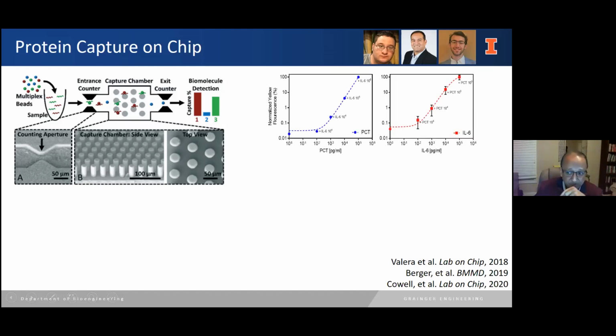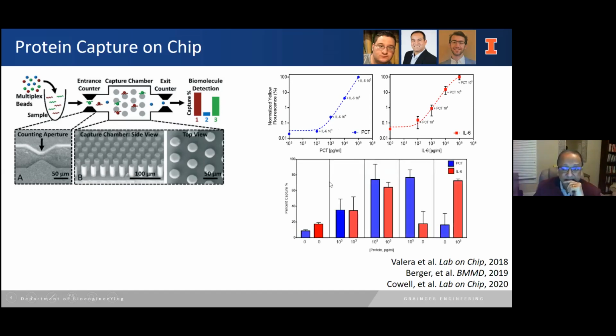Using that approach, which we've also published, we can measure PCT. So this is PCT with increasing concentration. We can also measure IL-6, which were two of the proteins that were in that panel that I showed earlier. And again, we can differentiate between high and low PCT in the background of the other protein.